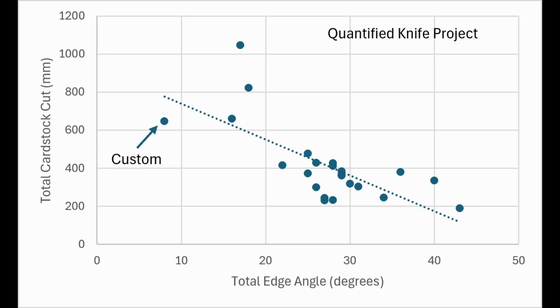The custom knife, however, had blue super steel, and it was at a very low edge angle, so 4 degrees per side, 8 degrees total, really, really acute. And it cut really well, 650 millimeters. When I tested blue super, I only measured 338 millimeters. But that was with a 30-degree edge angle. So the custom knife had an edge geometry that was selected for cutting performance and edge retention. It would also be more delicate and more likely to chip because everything is a trade-off. But the custom knife in this case cut better not because of special forging or magical heat treating, but because of the edge geometry.